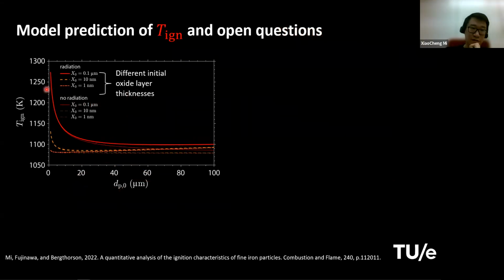And we did some parametric study. This is the ignition temperature determined using this model as a function of particle size. And different lines represent different conditions, like different initial oxide layer thickness. If the oxide layer thickness is very thin, you see there's not much difference as you go to very large particle size. And also the radiation effect is not very significant, because the thinner lines are without radiation, and the thicker lines are with radiation. The difference is quite small around the ignition temperature.